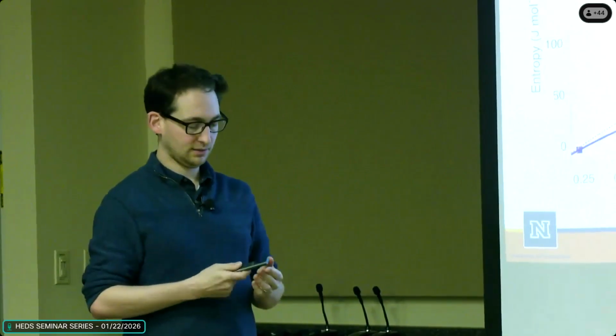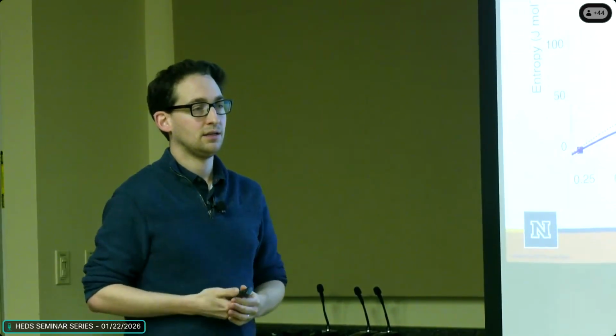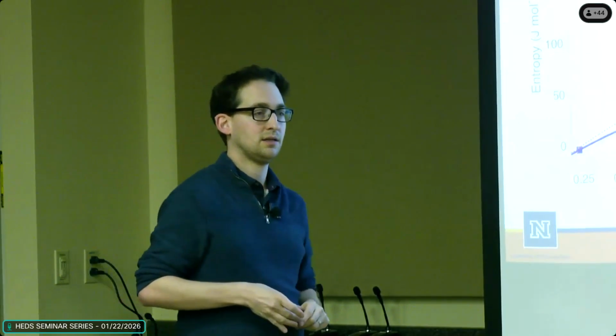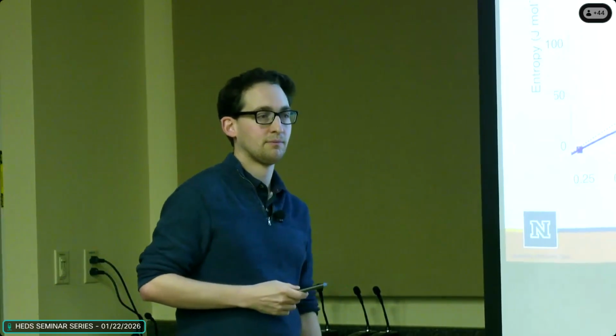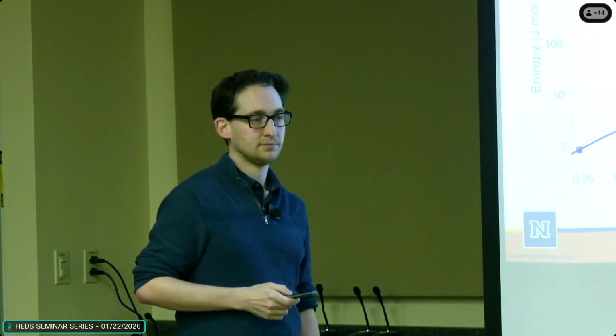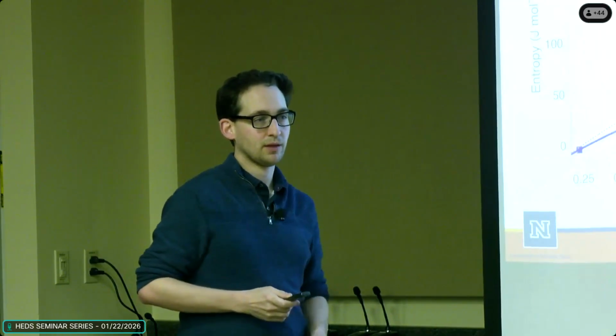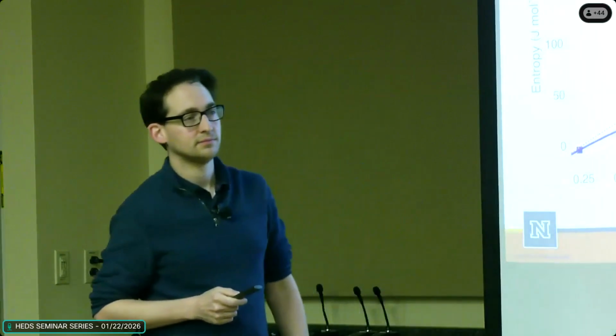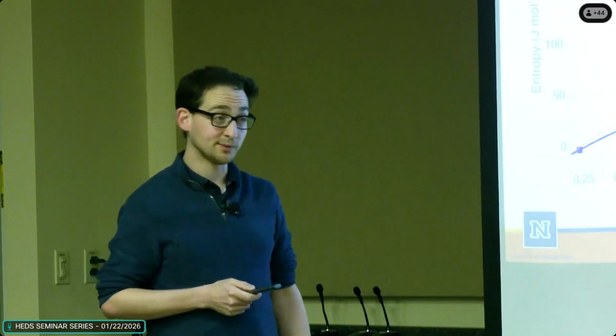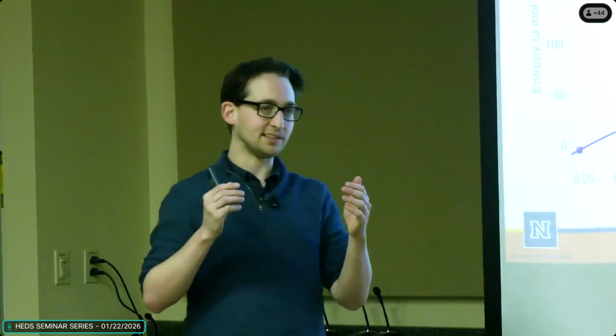We have a question online from Alfredo Correa Tedesco. One of the properties of superheating is that it is reversible. If you superheat without reaching a spontaneous transition and then cool down, nothing should happen. In your experiment, is it possible that the temperature that you measure is not really an equilibrium temperature, but simply some characteristic velocity of an inevitable, irreversible, Coulomb-like explosion? It's possible. It's absolutely possible that we're just measuring that. It is not reversible, right?